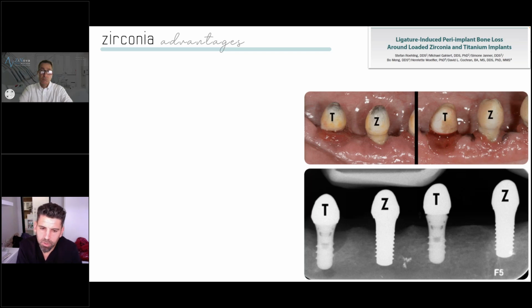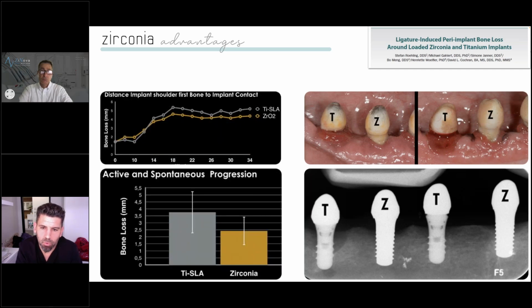And as you can see, zirconia implants will also develop peri-implantitis, but the incidence is significantly lower than what we see with titanium. We can see that the amount of bone loss around zirconia implants is significantly less than what we see around titanium implants, and both in the active and the spontaneous progression, zirconia implants behave better than titanium implants. So because of this higher biocompatibility and less affinity to accumulate plaque and bacteria, these implants are much more resistant to peri-implantitis. And that's one of the biggest advantages that we see as clinicians in using zirconia implants.